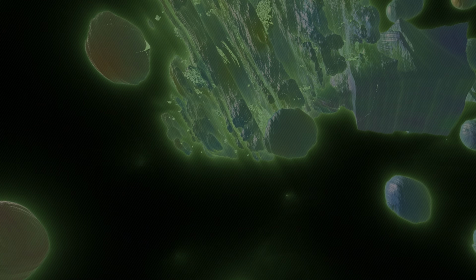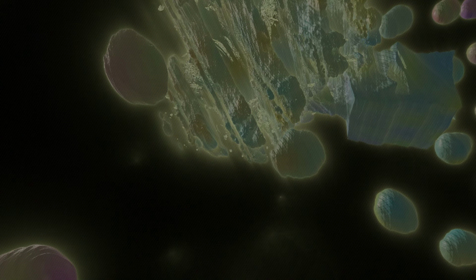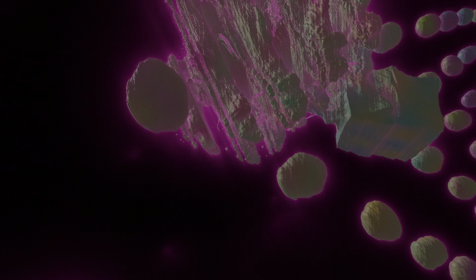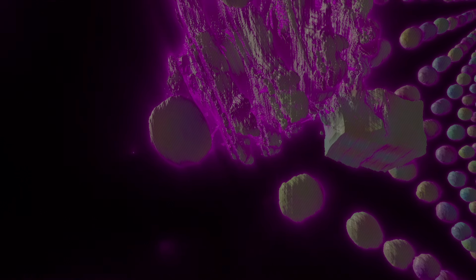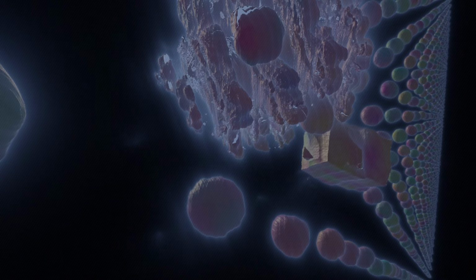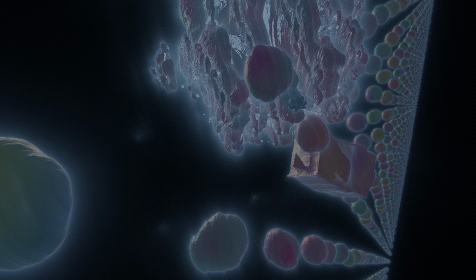Okay, so N processes just shuffle things around. What about umklapp? That sounds more dramatic. It is. Umklapp comes from the German for "to flip over." In these processes, the total crystal momentum is not conserved in the simple sense. What happens is the sum of the initial wave vectors, k1 plus k2, mathematically falls outside the first Brillouin zone. Because of the lattice periodicity, this gets mapped back into the first Brillouin zone by subtracting a reciprocal lattice vector, G. So it looks like k1 plus k2 equals k3 plus G. So the momentum effectively gets flipped back.